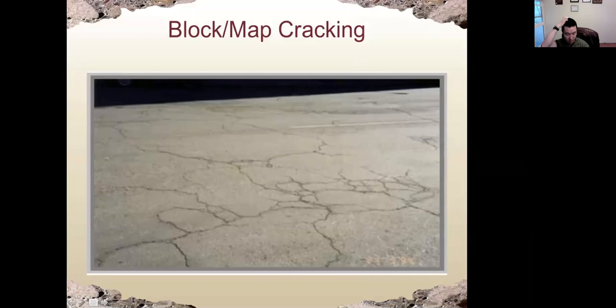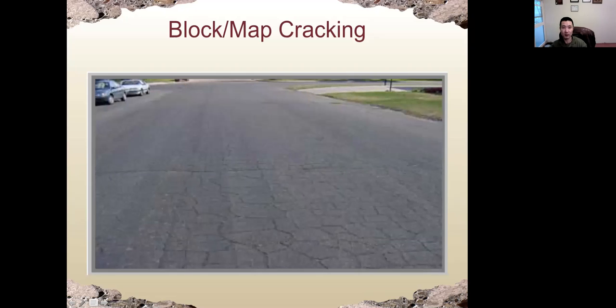This is also interconnected cracks. Due to concrete aging, too old, shrinkage of the pavement, or we have too many temperature cycles, the binder becomes aged and too stiff, too rigid, and that will cause the asphalt concrete to crack. We also call that block or map cracking, so we can see the cracks will interconnect to each other.